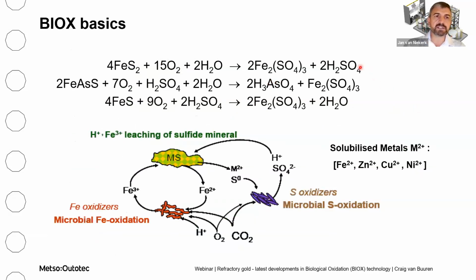The 3 important oxidation reactions for pyrite, arsenopyrite, and pyrrhotite are shown here. Important to note is the high oxygen demand during the oxidation of sulphide minerals. It's also important to note that pyrite oxidation produces acid, while arsenopyrite and pyrrhotite oxidation consumes acid. And this, along with the carbonate content in the concentrate, will determine whether the process is net acid consuming or net acid producing during bioxidation.